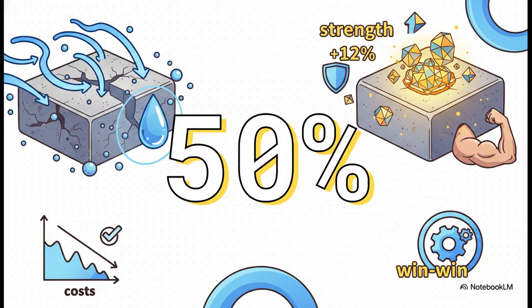So what's the real-world impact of that? 50%. By stopping those tiny cracks at the absolute source and blocking water intrusion before it even starts, future maintenance and repair costs drop by half, 50%. And while it's doing that, the formation of that CSH gel we talked about actually boosts the 28-day compressive strength by 12%. Just a massive win-win.